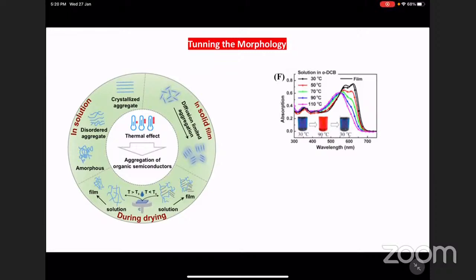Chemists, the humans who are making them, push them into the NIR range. And once you make them in the NIR range, they don't get solubilized so easily. But then we do all kinds of additional thermodynamics to make them soluble. Otherwise they stay in an aggregated state. So in the 30 degrees Celsius data, you see room temperature has a very strong excitonic, vibronic feature. But the moment you heat it up, you have more amorphous chains, and you have more amorphous chains at 110 degrees Celsius. But at 30 degrees Celsius, they are much more aggregated, and there are very strong vibronic peaks here.